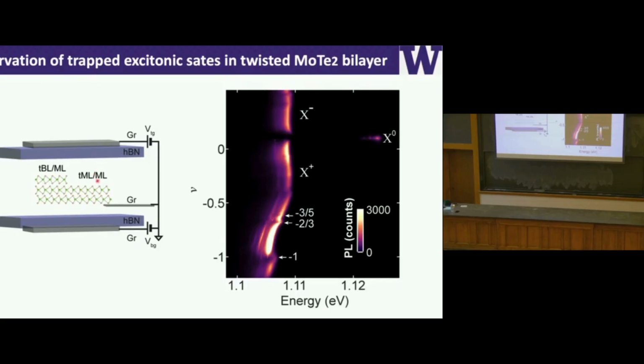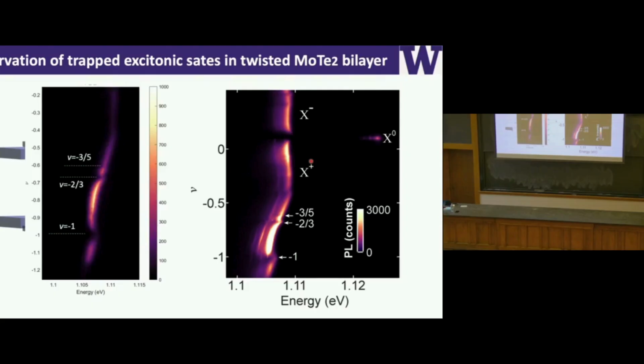On the right-hand side is the luminescence plot from this interface. If you're not familiar with this type of data, you probably cannot tell the difference. But let me compare these data with a clean sample I just showed you. You probably see the difference, right? In addition to the main feature, which is luminescence from free trions, in this new sample we actually have a replica on the low energy side. This replica has a narrower line width. That's the feature we observe.